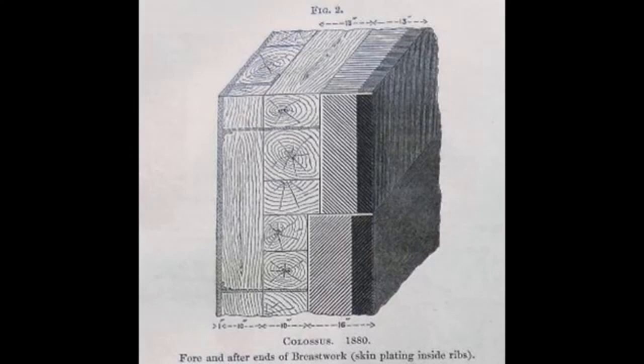Attempts were therefore made to see if making the steel a little bit softer might work, which would in theory allow the replacement of the whole belt with a thinner belt of softer steel. You wouldn't have quite the same increase in resistance that you would with the brittle steel, but it would still be better than iron on its own, and thus you could reduce the thickness somewhat. In tests, this seemed to be possible, but in practice, the steel was still far too vulnerable to breaking up under stress, these various issues frustrating early French and Italian efforts to get ahead of the game. With Britain at this point still the leading industrial power, the solution would eventually come from the UK, as in the late 1870s, the great steel-making city of Sheffield yielded up 2 engineers who managed to solve the problem independently.